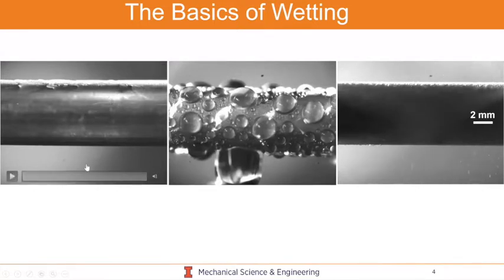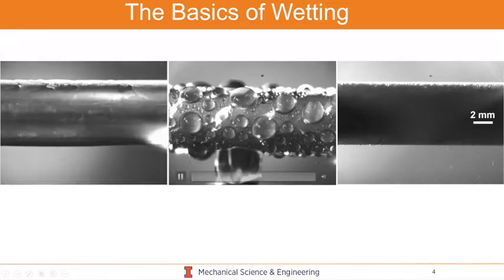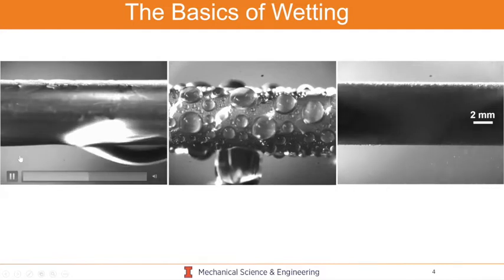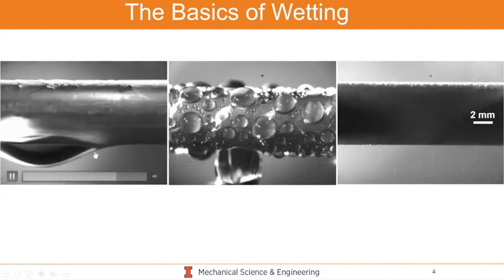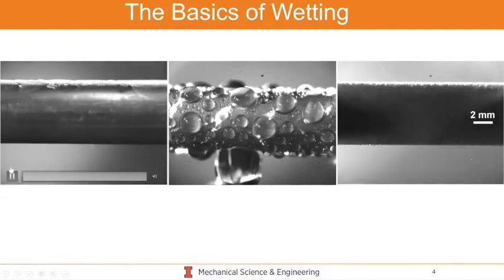And you can see that when it condenses, it forms this very thin film, and you can barely see any droplets forming on here. You actually see a droplet going, I'm just trying to play it here. You see a droplet rolling down the middle towards the left. That's just because this tube is slightly tilted. So the film actually accumulates and moves to the left.